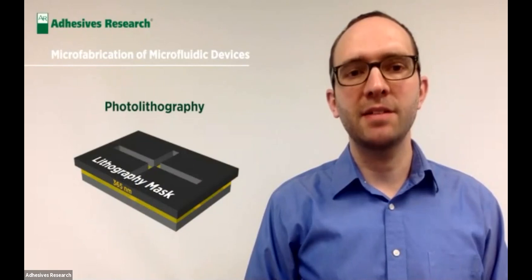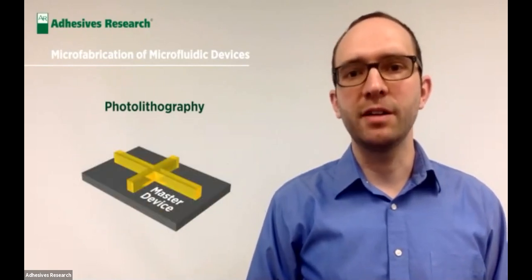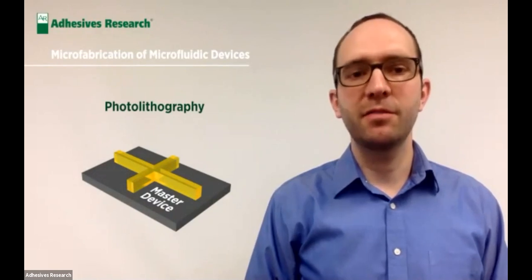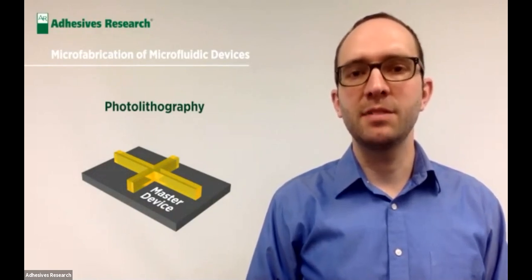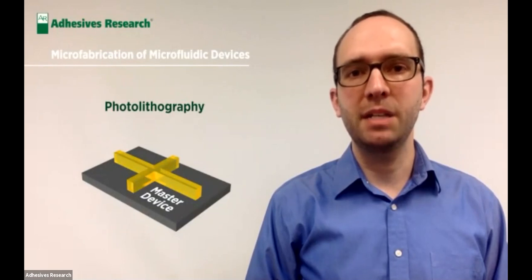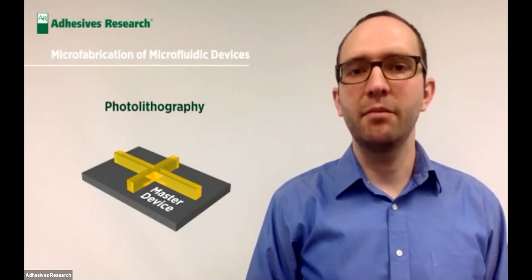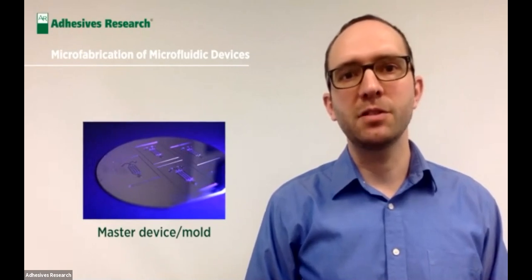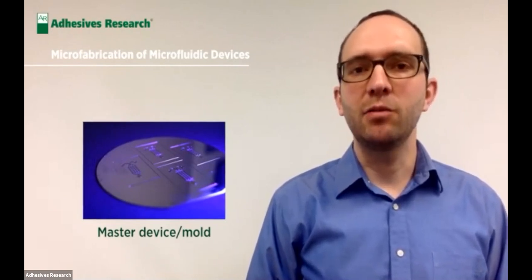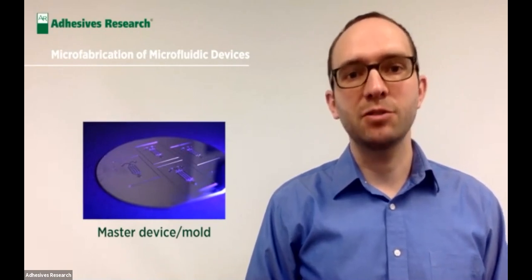Microfluidic devices are commonly prepared through a process known as soft lithography. It begins with the traditional photolithography approach, in which you take a silicon wafer, you spin coat SU8 or another type of epoxy material onto it, and then through a lithographic mask and UV light, you form your master device. This type of master device can then be replicated numerous times in the soft lithography process. That involves essentially casting PDMS onto the surface of the master mold, curing it, and then removing it from the surface. And then applying it to a glass slide surface after plasma treatment.